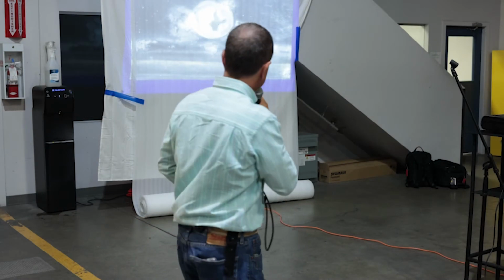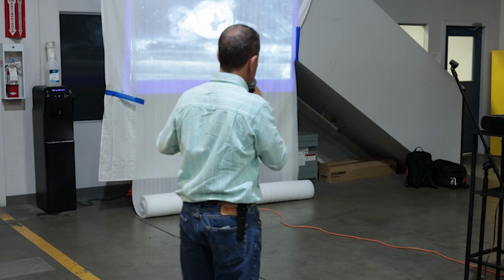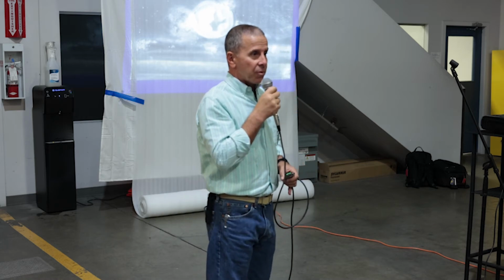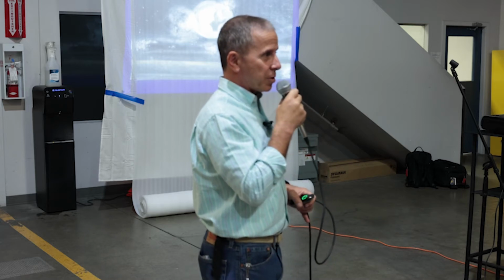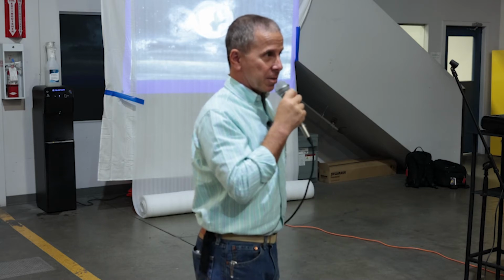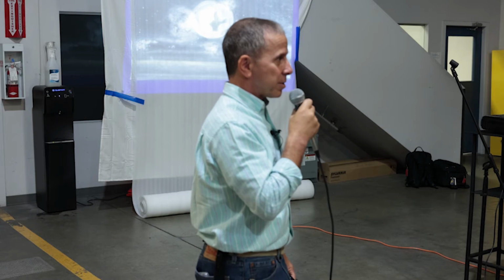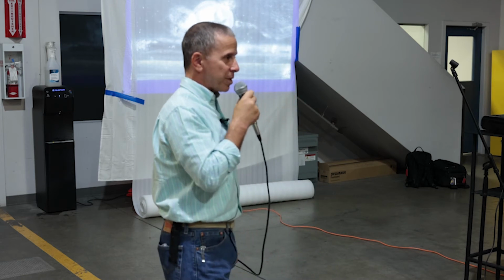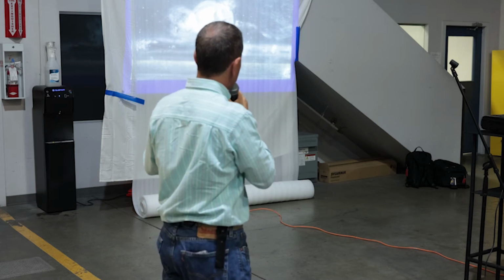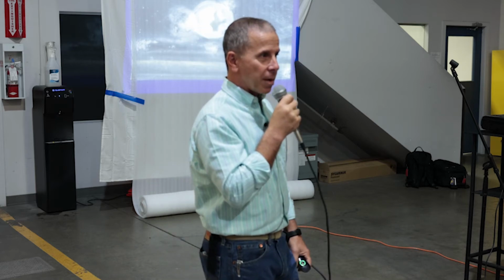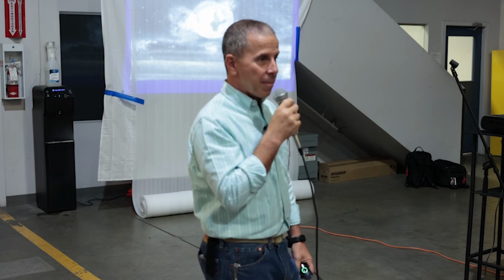In this example, we've got a stainless steel fastener that is in an aluminum track, and those two making contact with each other, and water penetrating the interface between the two, is problematic. Adding to this scenario, though, is the fact that it's a recess. So water that leaks into this area, or is exposed to water in this area, is essentially trapped. It is sitting in a puddle at the interface between the two different metals and exacerbating this problem.